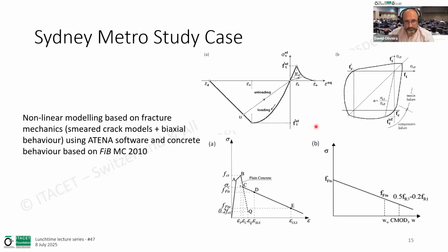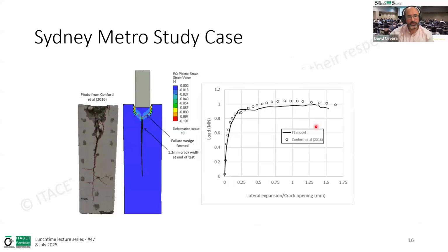the FIB Model Code. The first step we did, to be confident that our modeling technique was able to represent real cases and particular experimental work, was to simulate some of the tests done by Conforti in 2016. And we showed that, using of course their concrete properties, we could fully represent with that type of modeling technique what was happening with the test results, both in terms of load and crack opening, but also in terms of crack development and failure mechanism. You can see here the cone failure and the development of the splitting crack. And this gave us some confidence that we're on the right track.